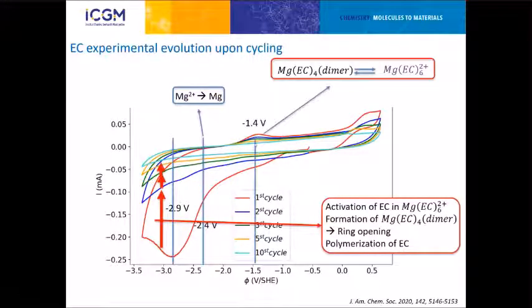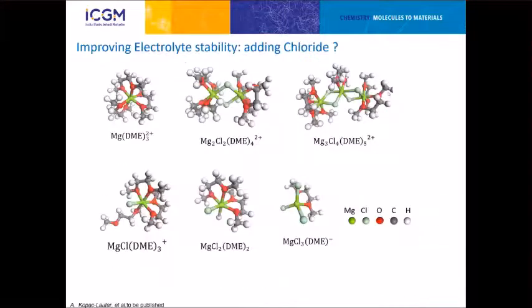In the second part, what is interesting also with ethylene carbonate is that we find a peak at around minus 1.4 that directly corresponds to the dimer-monomer equilibrium we previously found. So that's certainly one other indirect proof that things are happening with this kind of magnesium. So to summarize this part, mostly what is annoying is DME is not stable enough under reduction and just will